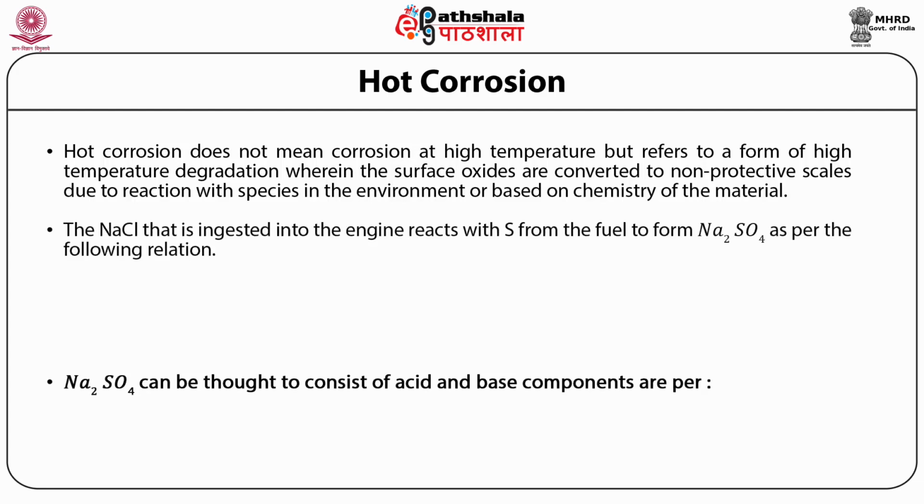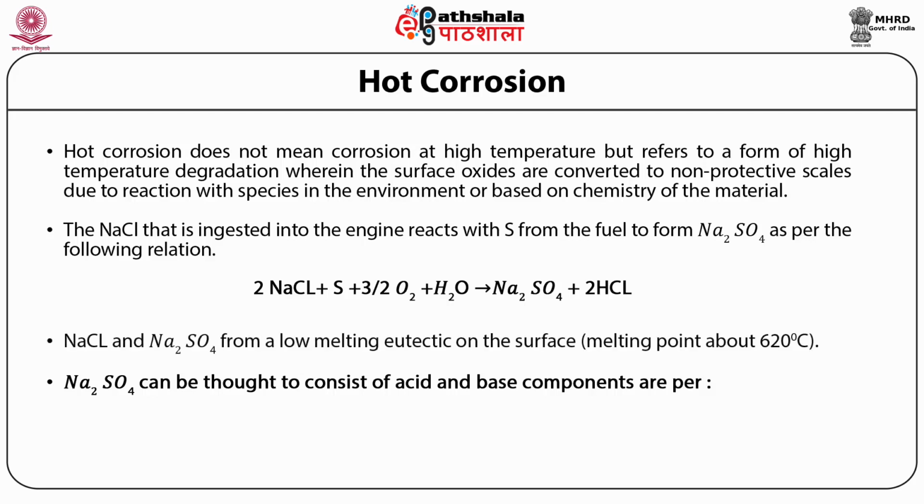The NaCl that is ingested into the engine reacts with sulfur from the fuel to form Na2SO4 as per the following reaction: 2NaCl plus S plus 3/2 O2 plus H2O gives Na2SO4 plus 2HCl. NaCl and Na2SO4 form a low melting eutectic on the surface. Melting point is about 620 degrees Celsius.